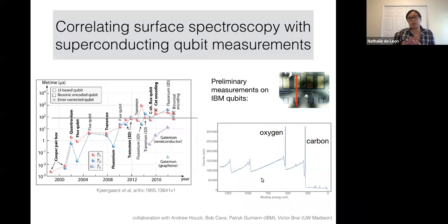Yeah, so these measurements always start with spectroscopy. We just sweep the frequency of this tone and then see what's there. But the tone that we ended up using here, or the signature that a lot of people see, is just S equals a half, g equals 2. So it's selective, but the vast majority of electronic spin defects are also going to be g equals 2, S equals a half. So it could be that we're still addressing several different populations that are heterogeneous. But I can tell you, we don't see any obvious hyperfine peaks associated with it, so we know that they're not nitrogen-containing defects. But other people have done DEER spectroscopy in heavily nitrogen-doped samples where you can clearly see that you're looking at something with nitrogen, for example.